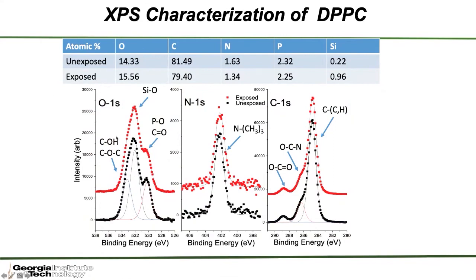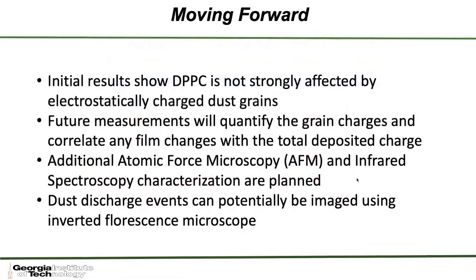Then, depending on the energy of those ejected electrons, we can assign the various peaks in the envelope to specific molecular bonds. And what I'm actually showing is a before and after, where the black is unexposed, the red is exposed, and we don't see very big changes between those two. So with the XPS technique, maybe it's not super clear, but we are pushing forward, trying to determine if there's a better way of looking at how these grains affect these molecules. So moving forward, the initial results show that DPPC is at least not strongly affected by these dust grains, although there's still some work that we're doing to look at this.